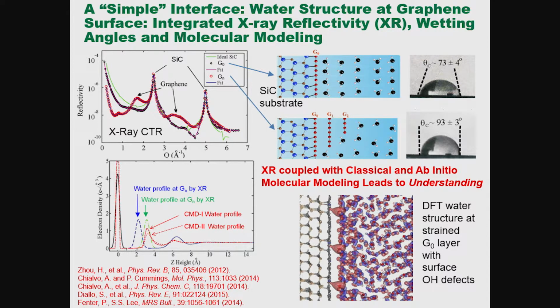So this is an example of a simple interface. This is X-ray reflectivity work. This is a logarithmic scale of reflected X-ray intensity from graphene formed by thermal annealing on a silicon carbide single crystal substrate in contact with water. These are the Bragg reflections. So we're looking at the energy between Bragg reflections, and the shape of this inter-Bragg crystal truncation rod is very sensitive to the surface structure.